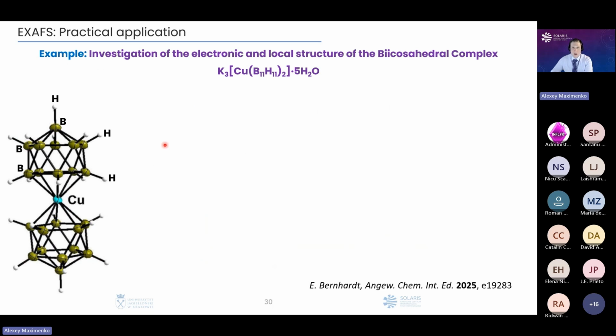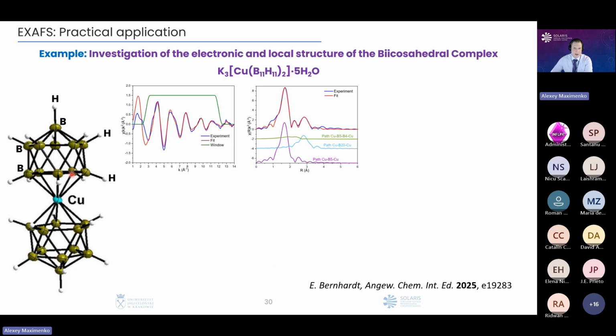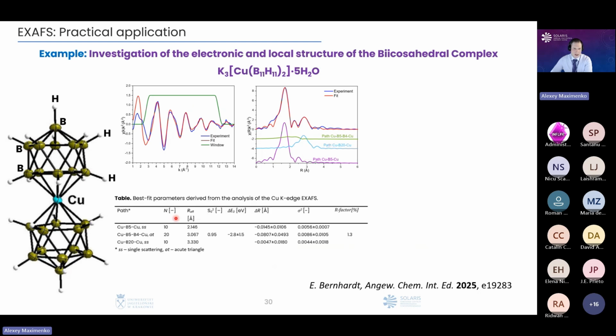For example, we have a quite complicated compound where we have a copper which is surrounded by some kind of a boron cage. And using the procedure which I showed you above, and by the fitting, we could understand how many neighboring boron atoms there are. For example, here you could see interaction copper, boron, copper. Here, this is some kind of multiple-scattering influence, copper, boron, boron, copper. We could investigate how many such neighboring atoms we have in our material, what the distance is between our absorbing atom and neighboring atoms, and what kind of distortion we have in our material.